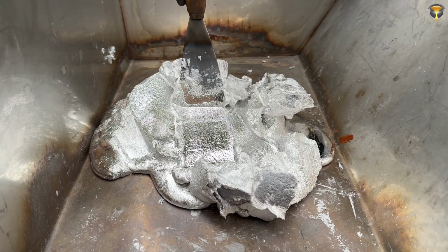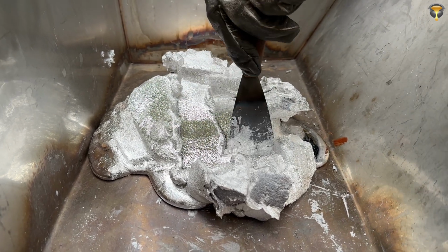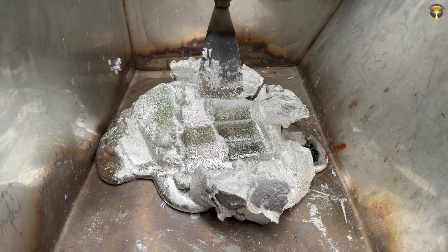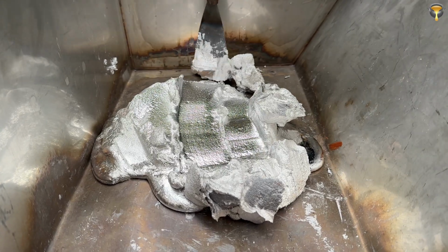Another interesting aspect of this is that people try to get something that looks like a semi-solid. And the problem is that if you start to look like what you think is a semi-solid, like a porridge, then you're way too high in solid fraction. The second thing is that the normal work instruction to get rid of problems in high-pressure die casting is shooting faster, shooting hotter, and shooting with higher and higher pressure.